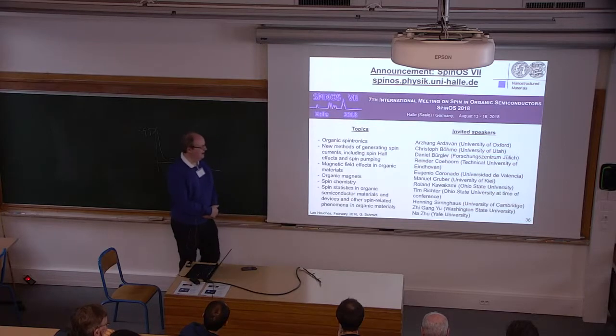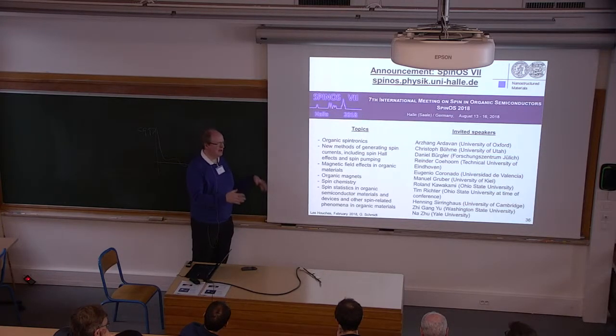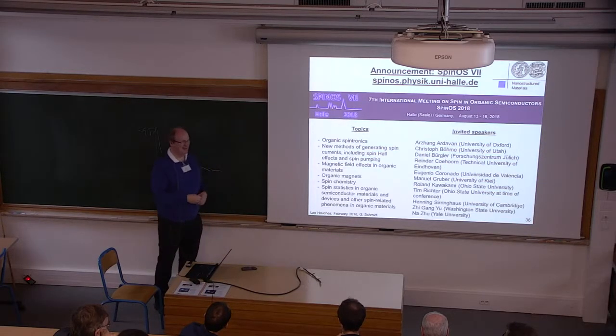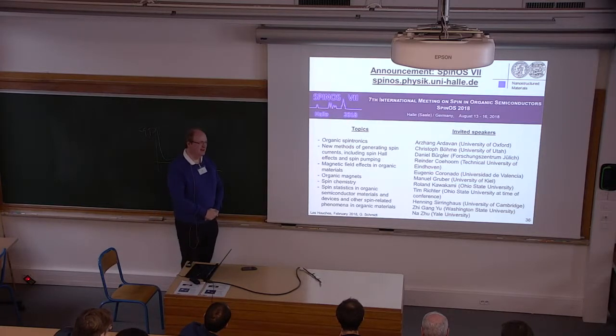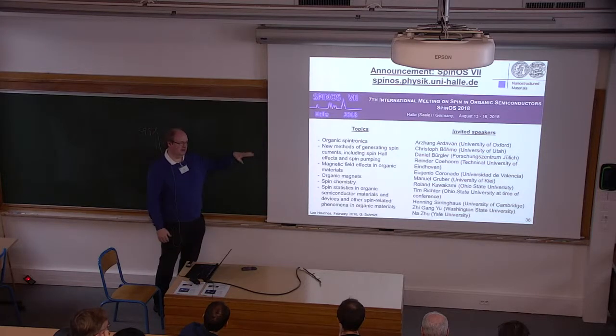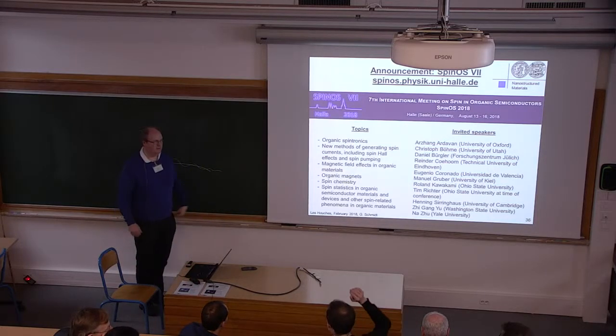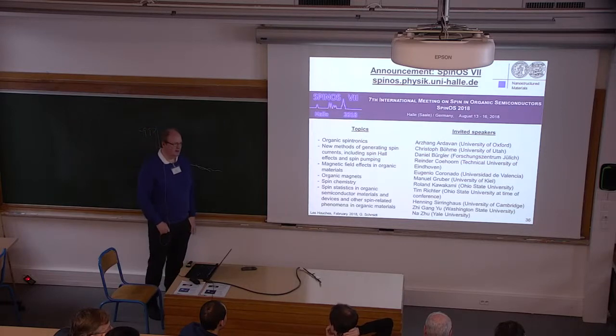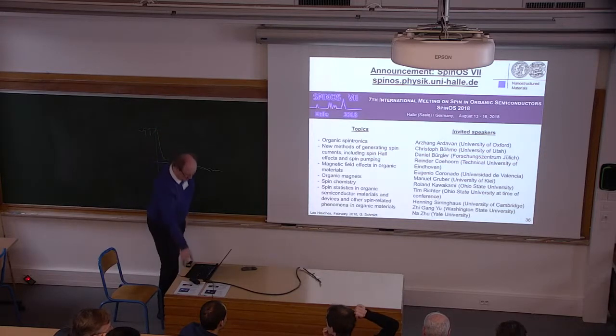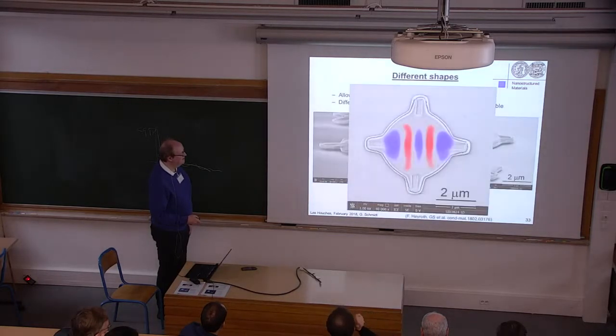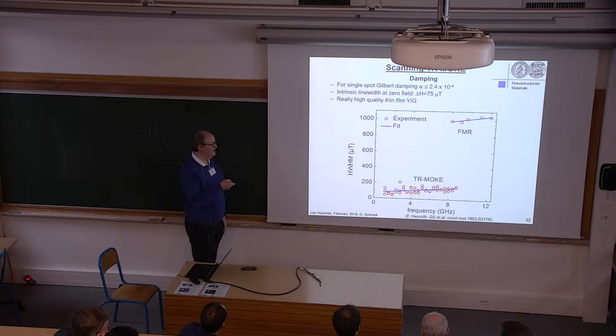I know, and I think you also see it in the paper. Sometimes you have very low damping or very low growth of the line width with frequency, but the intrinsic line width is very large. But in this case, the intrinsic line width is 0.7, and we can say that this is low damping. Yeah, sure, I agree completely. So this is, by the way, also for the layers. This is an example where you have narrow lines and low damping. I say that as a general remark, because a lot of people, it's true in metallics, but I think in garnet you have to be very careful with this frequency dependence of the line width. Yeah, for example, this would not be so telltale here.